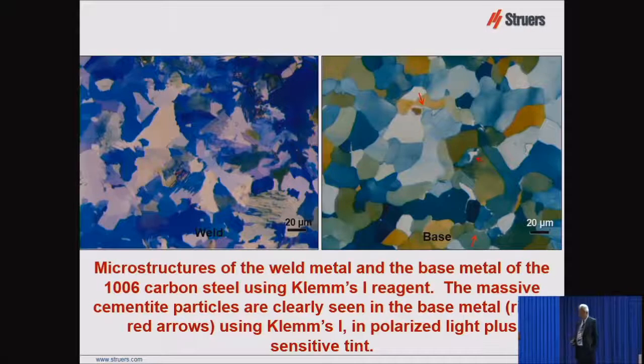And here's two of these areas using Klemm's number one, developed by Heinz Klemm of Germany in 1954. Or at least he published it in 53, I think, is when he published it. But I believe he actually developed the etchants a couple years before. So here's the weld metal, and there's a lot of ferrite in there, and you can see the acicular structure that's in there. And here's the base metal. There's cementite right in this area where the arrow is pointing to, and that cementite is not colored by Klemm's.